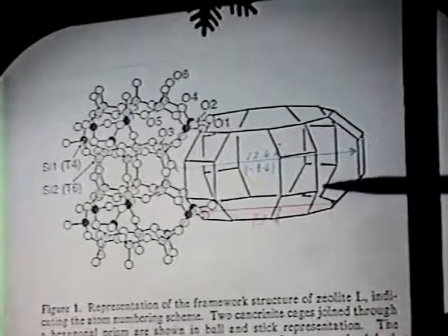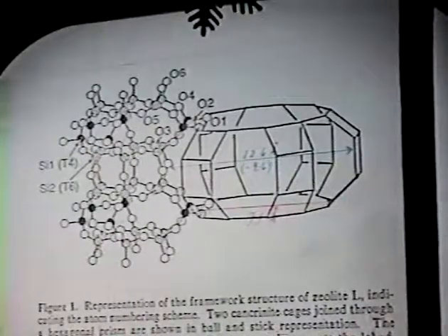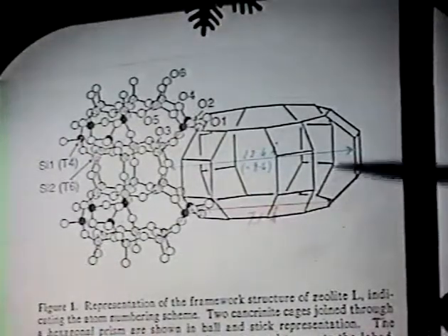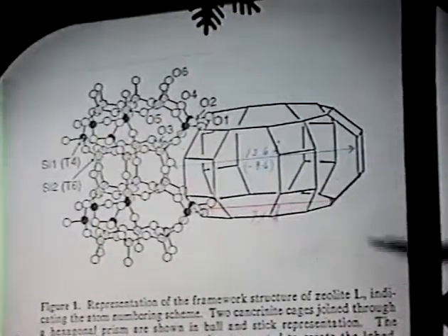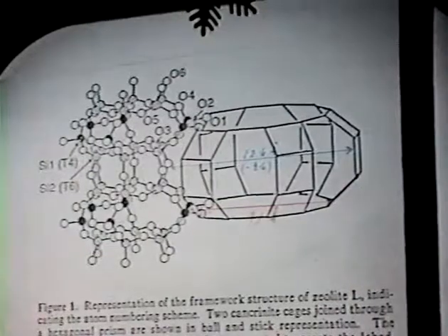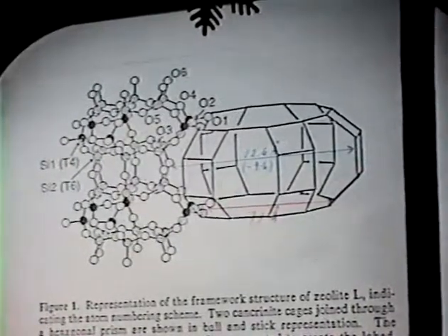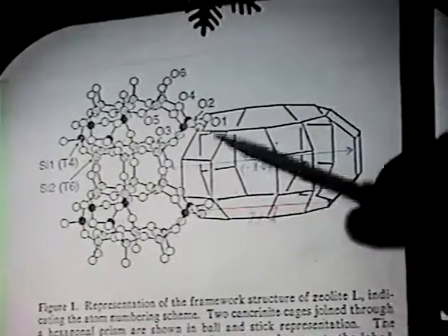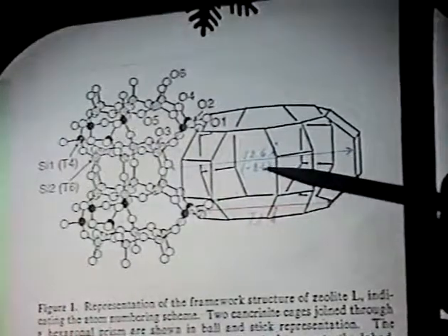There are 6 cation positions, of which 3 would be filled if it were a univalent cation that you had in there, and so that would decrease this size to about 10 angstroms. But in fact, this is a barium or magnesium, and what happens is, of course, for every barium or magnesium you put in, you take out 2 potassiums, and then when you calcine at high temperature, you move the cation out of the parallel channels into these cancrinite cages. So, in fact, on average, the cages have got to be somewhere between 10 and closer to 12 angstroms in diameter.